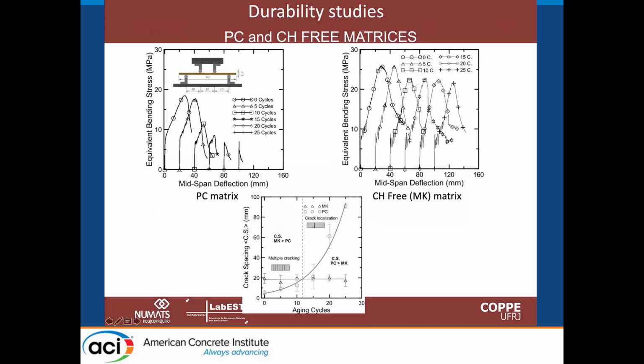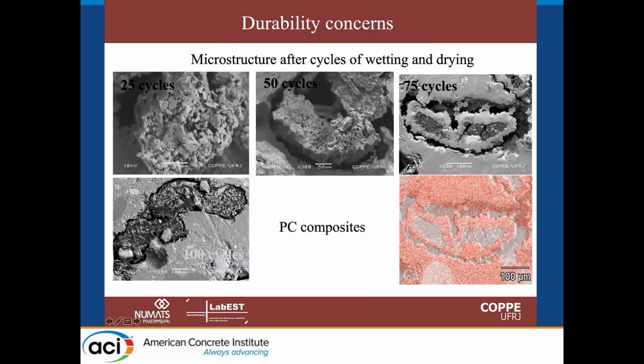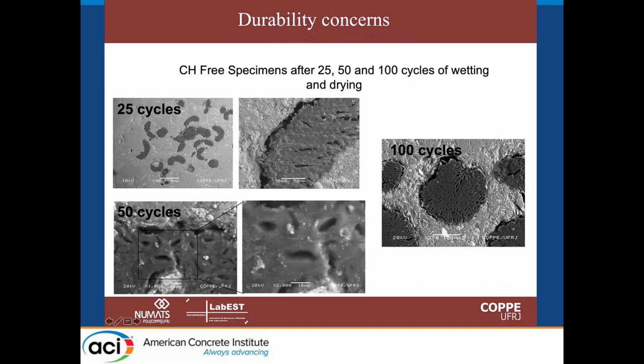You see here on the left in this picture, if we do not replace cement by pozzolanic material to consume completely the calcium hydroxide, after a few cycles, even after 10 cycles, we can already see the decrease in the post-cracking behavior. On the other hand, when we use the CH-free matrix, we keep very much the same performance over time. So you see here what happens in the Portland cement matrix with vegetable fibers. Calcium hydroxide migrates to the microstructure of these fibers that are porous, and we have mineralization. That's why we need to use metakaolin, so we can keep the integrity of the fiber, like we can see in this microstructure here in this picture.